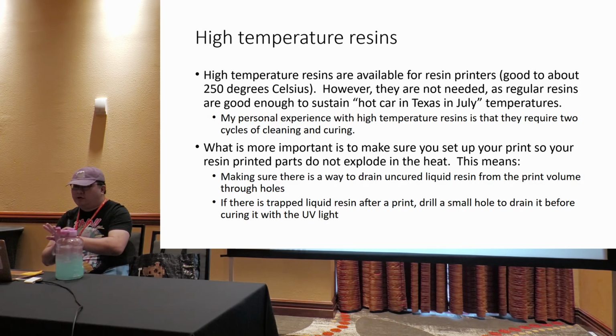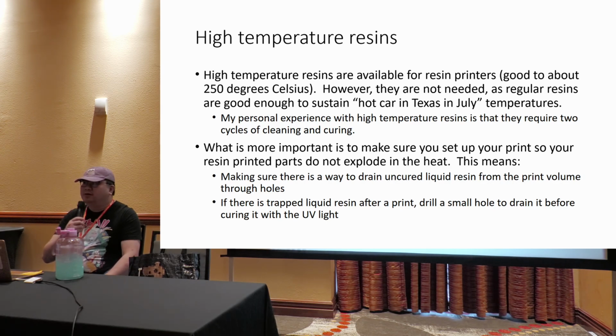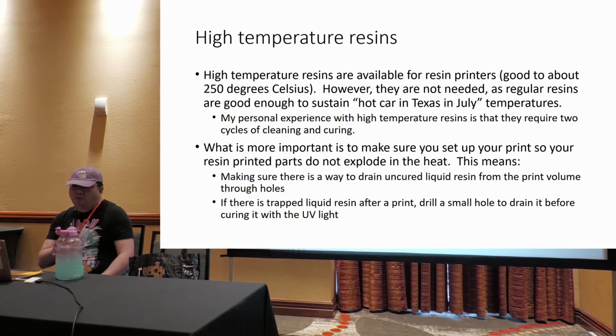If you do not drain it out, the minute you subject it to high heat, the resin still cures. Remember, these resins cure not only using UV, but they also cure using heat. So once it gets heated up, it blows up. It shatters, you have a good mess in your car, and you will probably spend hours trying to fish out resin pieces. So what is more important is making sure your print is done in a way that your resin parts do not explode, by draining all unused resin.